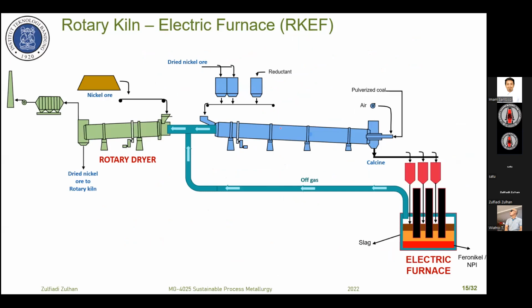Now in the current technology, there is a trend to utilize the heat from the off gas from the furnace and also from the rotary kiln, and they can transfer it directly to the rotary dryer as the source of energy. Similar is here. In this case, we need only 1 stack at the end. Theoretically, we need only 1 stack, but very often they also have 1 stack here, first, what you call a spare. If there is some trouble here, they can do the bypass. They can send off gas to this stack. If everything is normal, we use only 1 stack after the rotary dryer, and 1 dedusting system and 1 ID fan.